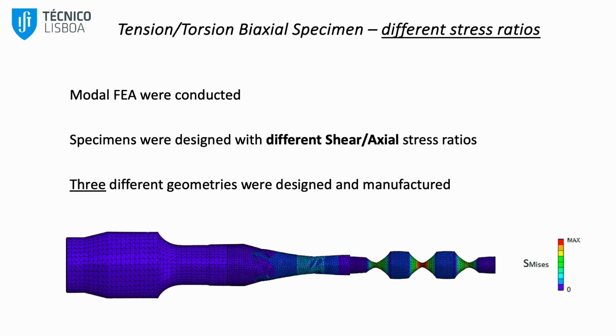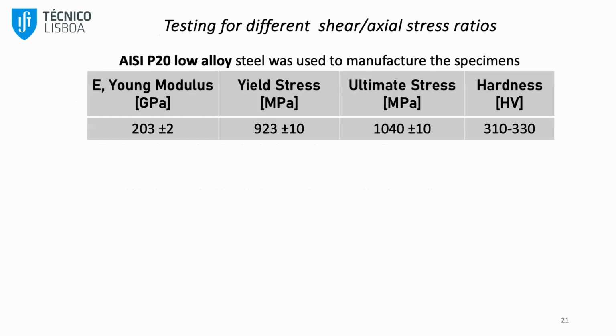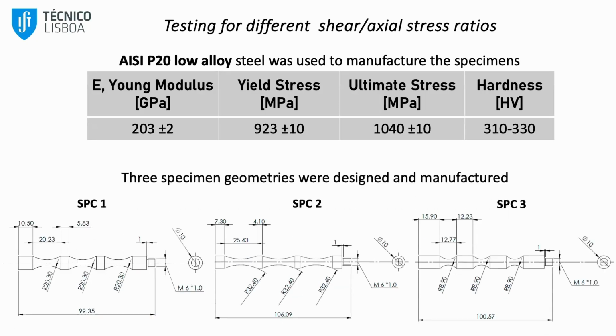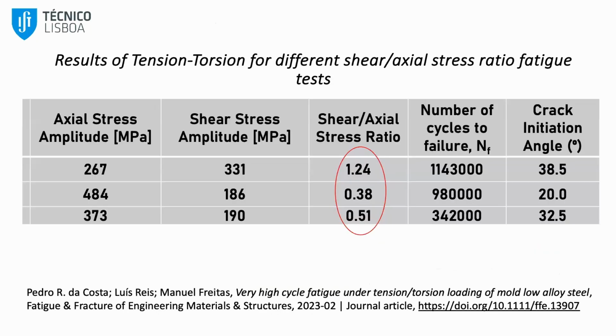and we manufacture 3 different geometries. Here the material that we have considered in our study, some mechanical properties, and here the 3 different specimens. As you can see, we have different lengths here, also different lengths here, and the radii are also different. Of course, we are talking about not so big differences, but we have 3 different specimens that allow us to consider and to apply different stress ratios. Okay, so here the axial one and the shear stress component.